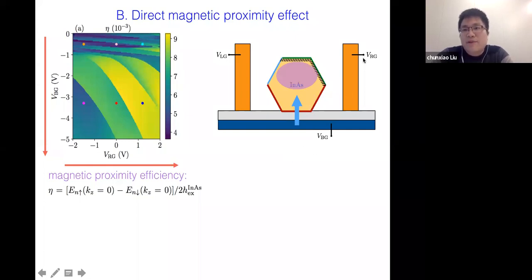And at the same time, if you make the right gate voltage more positive, it will attract the electrons to the right. Thus, in the end, the electrons will tend to be confined at the indium arsenide europium sulfide interface, where the direct proximity effect is the strongest. So that's why there's such a trend in general.